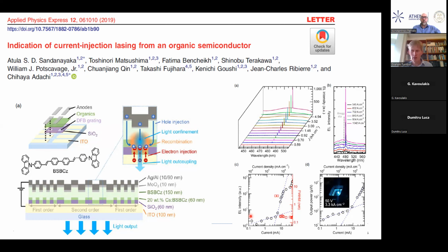But it was not able to show a very well defined laser beam from the device, and it didn't last for very many pulses, because in this sort of approach, you're really stressing these organic semiconductor materials to do many things all at the same time, and they found that the device would only run for a few tens of pulses before it would stop operating. So it's a very difficult thing to do and to do successfully.